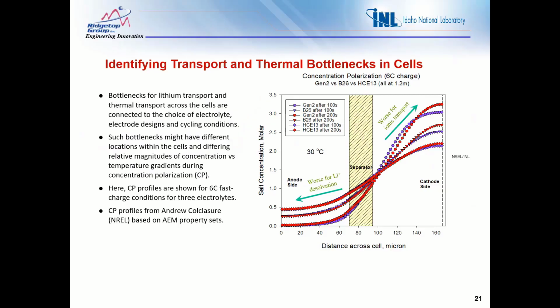So this reiterates what I said about paying attention to what happens to the electrolyte during fast charge. These are called concentration polarization plots. This is what happens to the electrolyte as you run it through an aggressive charge protocol. In this case, it's a 6C charge, taken about 100 or 200 seconds into the 6C charge condition, showing how the electrolyte is starting to polarize and form these different concentration gradients. These profiles were provided by Andrew Colclasure out of NREL. Andrew and I worked together on this fast charge program for DOE, and I provide him the electrolyte properties, and he runs his cell model and then gets out these types of profiles.